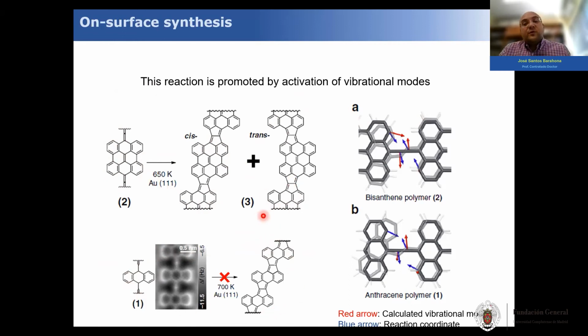Well, for that, we ran calculations for the vibrational modes of the system. And as you can see here, the red arrows are the vibrational modes, and the blue arrows are the reaction coordinates. And for the case of the bisanthene, you can see that the vibrational modes almost overlap with the reaction coordinates, whereas in the case of the anthracene, these modes don't overlap. And this is the other explanation of why these aromatic polymers cannot undergo this transformation into forming the pentalene linkers.